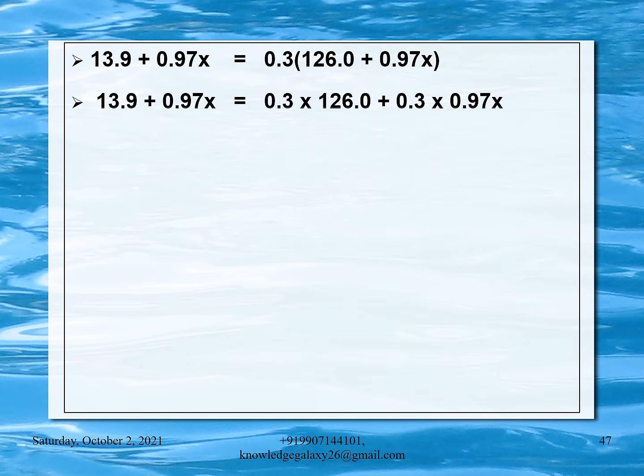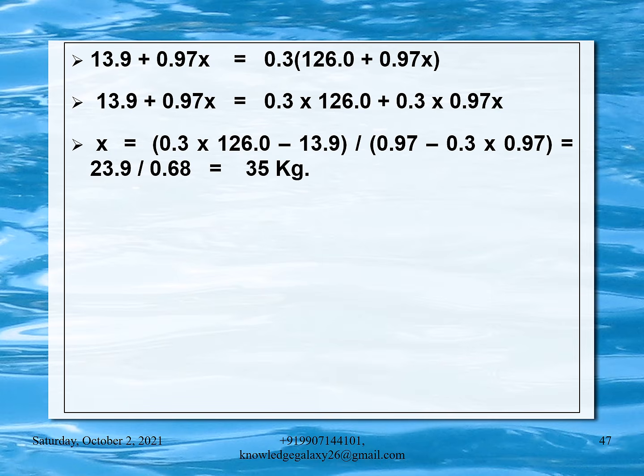Let us now further solve this equation. 13.9 plus 0.97x is equal to 0.3 into 126 plus 0.3 into 0.97x. So further solving this equation gives x is equal to 0.3 into 126 minus 13.9 whole divided by 0.97 minus 0.3 into 0.97 is equal to 23.9 divided by 0.68 is equal to 35 kg. You can further calculate all the data to balance the equation.